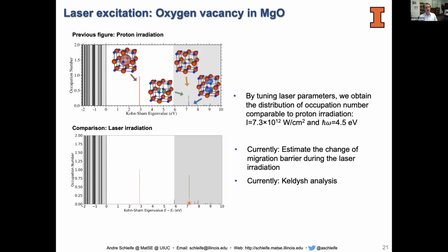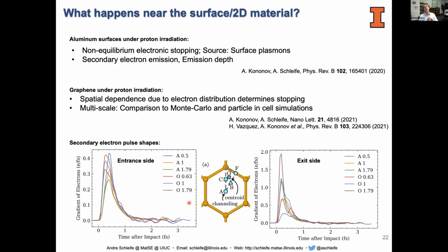The second interesting development is related to two-dimensional materials. So I showed you in my motivation slide for this part of the talk that people use these ion beams, and also people use laser beams to modify or to create defects in two-dimensional materials. And so we did two things, I would say. One is we looked at how proton beams affect very thin pieces of aluminum. So that seems artificial, and you probably tell me, okay, aluminum is not a 2D material. I agree.